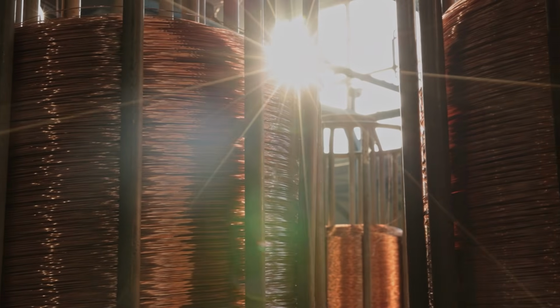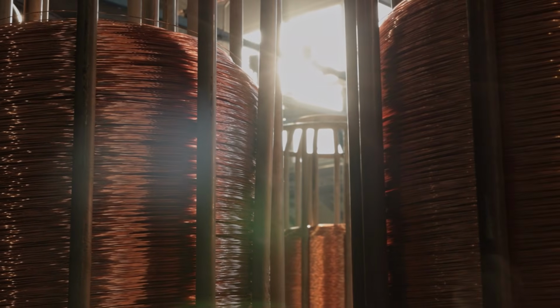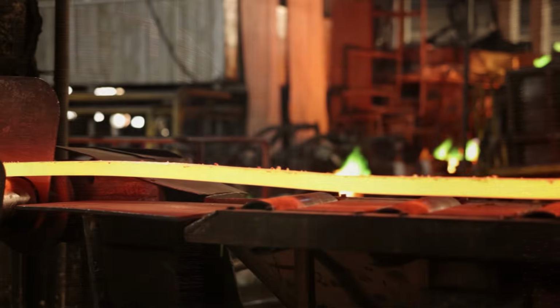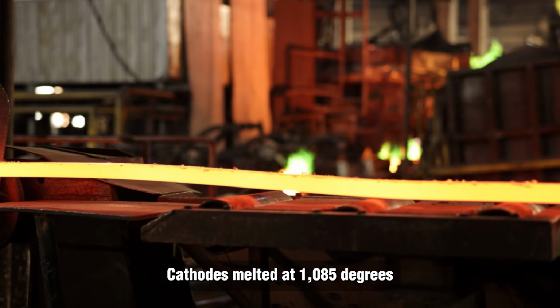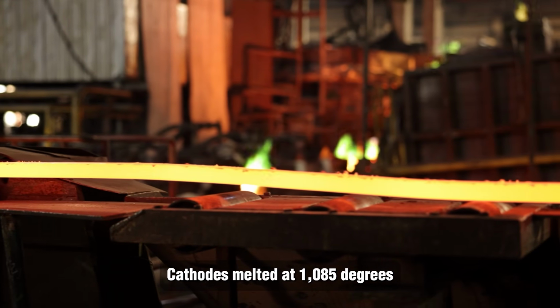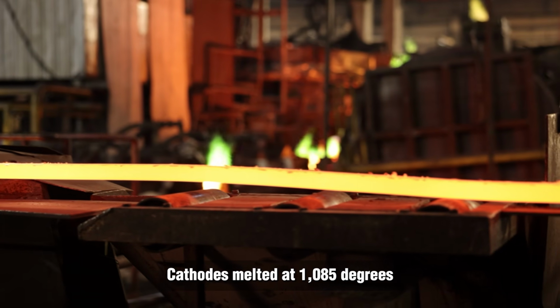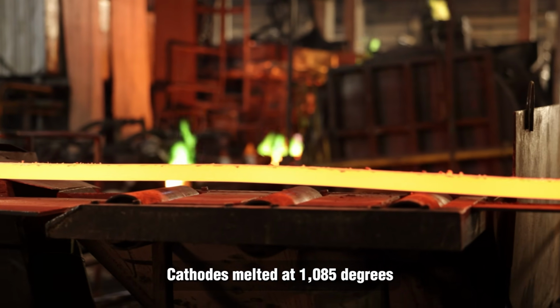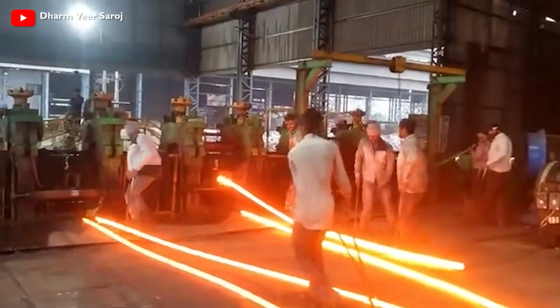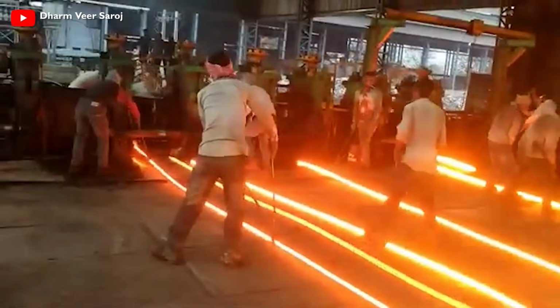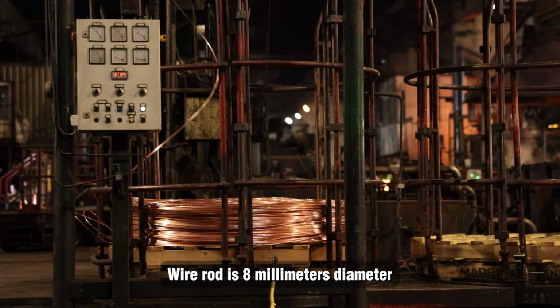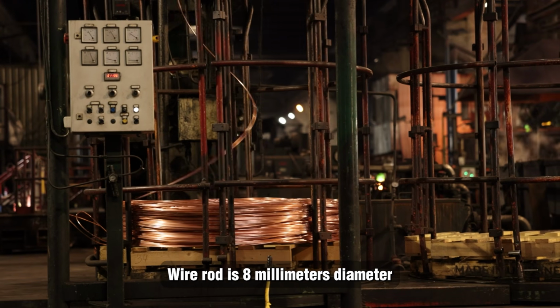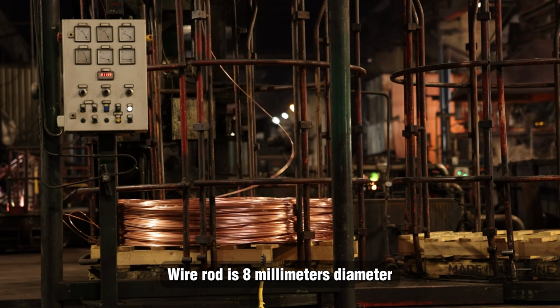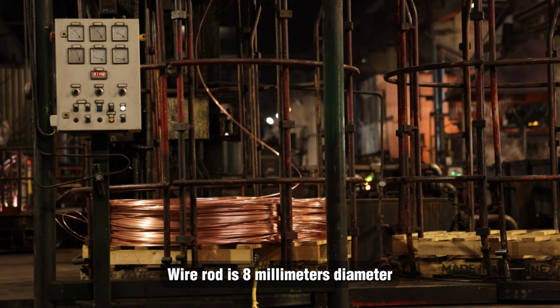Converting copper cathodes into wire rod involves continuous casting and rolling. The cathodes get melted at approximately 1,085 degrees Celsius and flow into a casting machine where the metal solidifies into a bar shape. The freshly cast bar immediately enters a rolling mill containing multiple roller stands that progressively reduce its cross-section while increasing its length. This process transforms cathode copper into wire rod, typically 8 millimeters in diameter, producing thousands of tons daily.